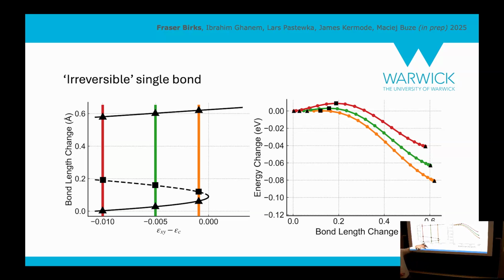And what you can see again is, these things were done separately. So the NEBs, which are the colored curves, agree really nicely with our predictions in energy from our continuation. So once again, this is a nice little validation, at least in the case of continuation, for these single bond methods. We tried following both curves much of it.